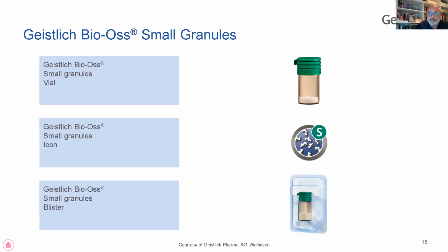With these, I like to mix it, which you will see the handling of it in a moment. I like to mix this with some saline, which is the indicated use. Everybody should do that. Sometimes we'll use some of the patient's blood to mix in there too. And realistically, you want to remove enough moisture so it has a sort of a wet sand feel to it. It shouldn't be too dry because then it sticks to everything and it's hard to handle. Having a bit of moisture and just a little bit of moisture on the surface.